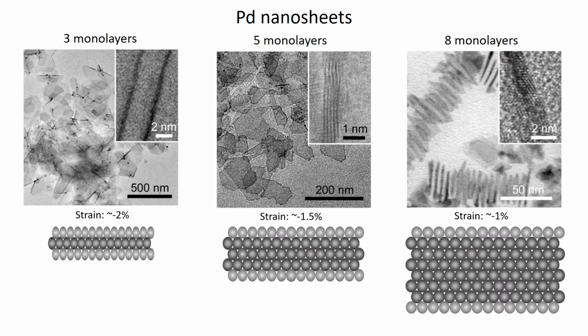to 1%. Our electrochemical tests indicate that these nanosheets are highly active for fuel cell reactions, in agreement with the computational predictions. For example, the 5 monolayer nanosheets can enhance the catalytic activity up to 50 times in comparison with the commercial catalysts. Thus, generating and tuning the strain of electrocatalysts by utilizing intrinsic surface stress is a promising strategy to boost the performance of fuel cells and other electrochemical devices.